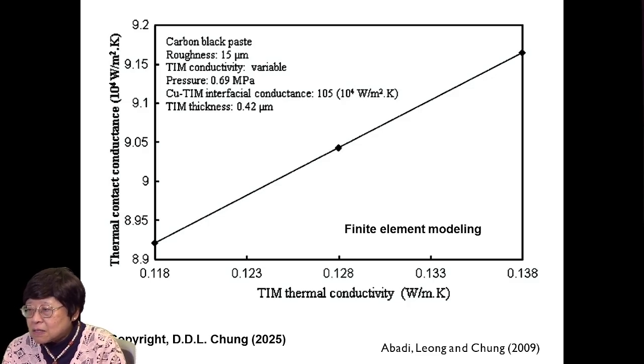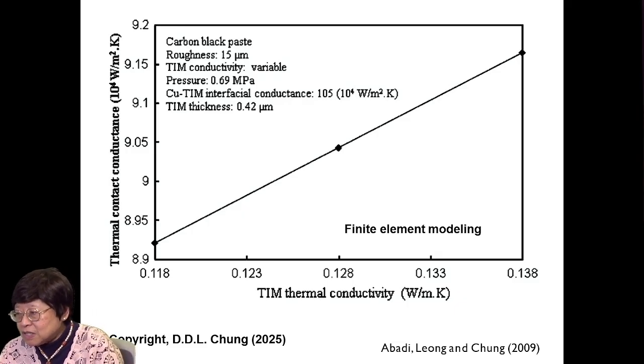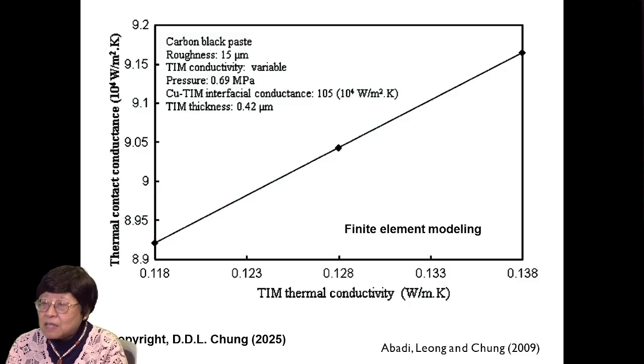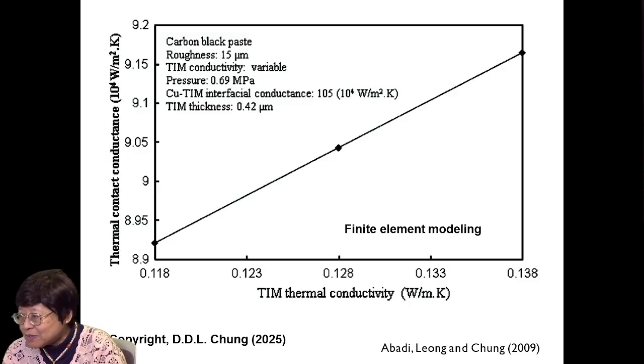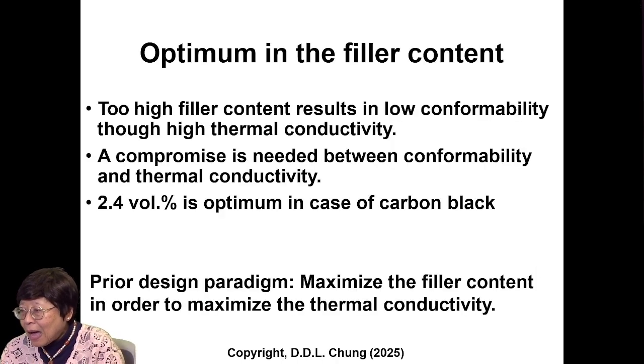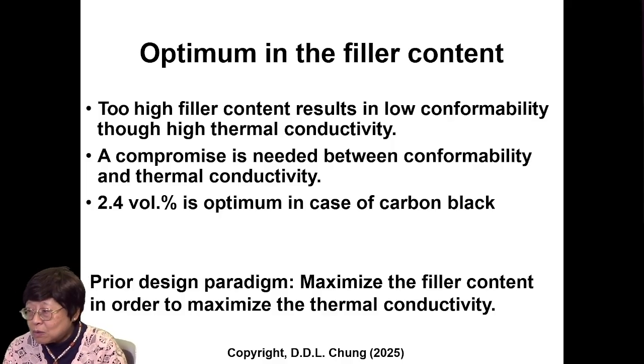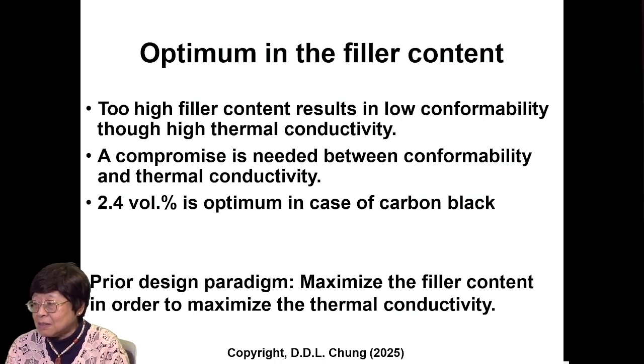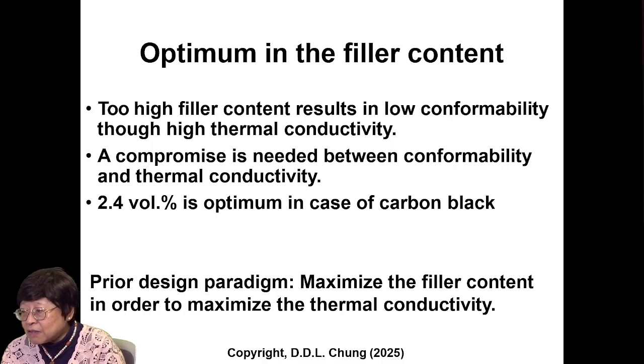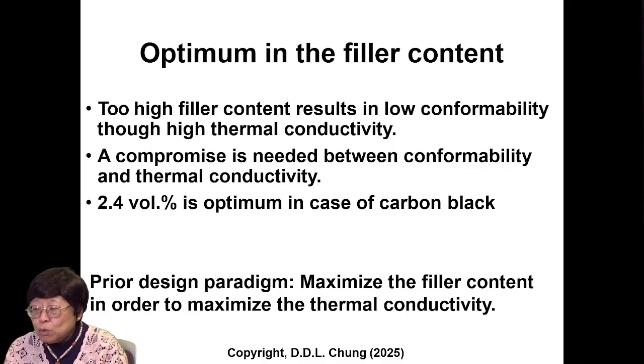The thermal contact conductance, which is the inverse of the thermal contact resistivity, increases with the TIM thermal conductivity with all other conditions fixed. That's kind of obvious. However, too high a filler content results in low conformability, though high thermal conductivity. So a compromise is needed between conformability and thermal conductivity. In case of carbon black, the optimum is 2.4 volume percent, not very high.